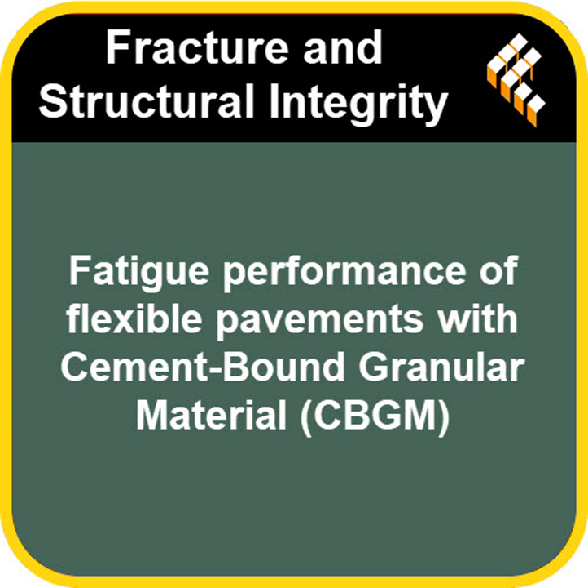Now, for flexible pavements, we primarily look at two main failure criteria. First, the cracking of the asphalt layer. That happens because of tensile strains at the bottom, the pulling apart motion when a wheel passes over. And second, the formation of permanent ruts or deformations. That's linked to vertical compressive strain down at the subgrade level, so the pushing down, the compacting effect into the earth beneath the road structure. However, for these cement-bound layers like CBGM, there's also another risk, vertical crushing.